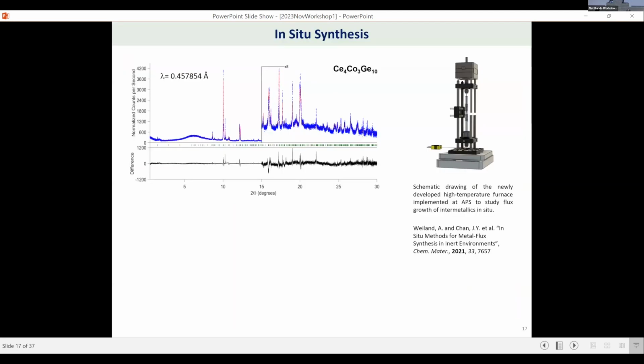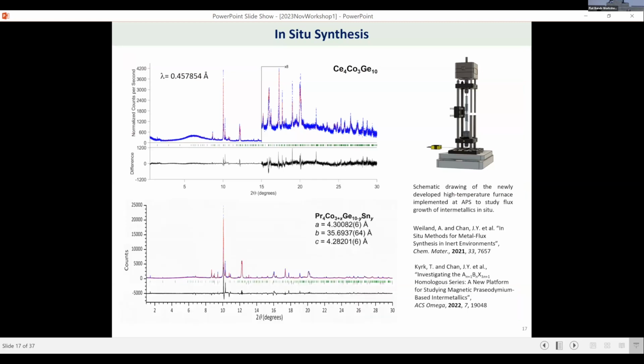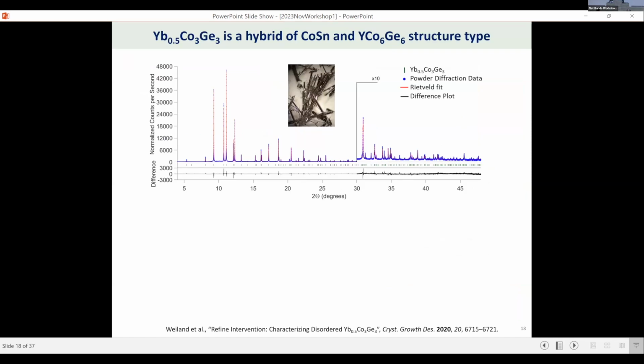So we're able to get very nice powder diffraction patterns, even with tin. Tin actually absorbs, for some reason. But nonetheless, we're able to identify a new member of the series, and that's how we really decided that we now have a new homologous series to work with. But another thing we also thought about was, well, our student was at the beamline, and we had a ytterbium phase, and we thought, cerium, ytterbium, what do we have? And we had gotten a compound. It turns out that this is a hybrid of a cobalt tin and a 166 structure type compound. We have beautiful crystals, but the structure was more complex.